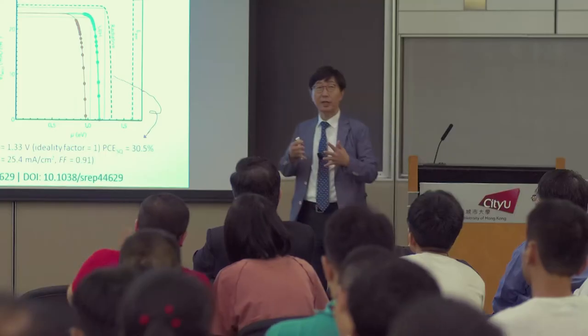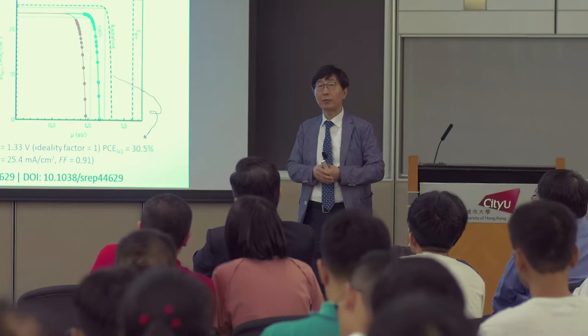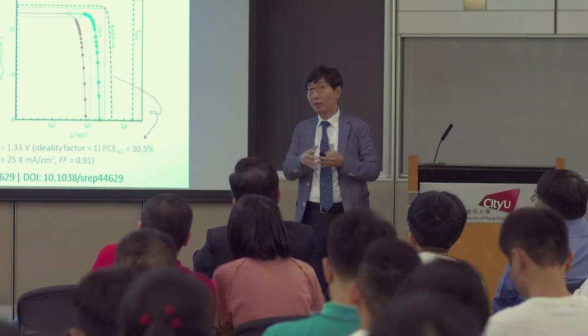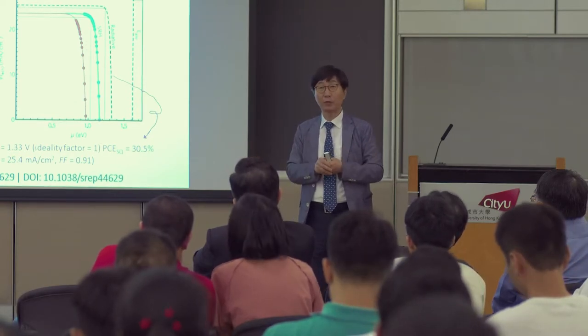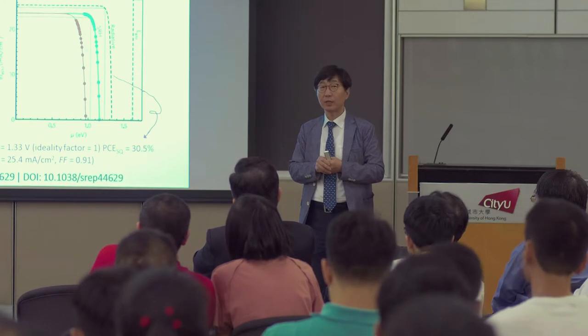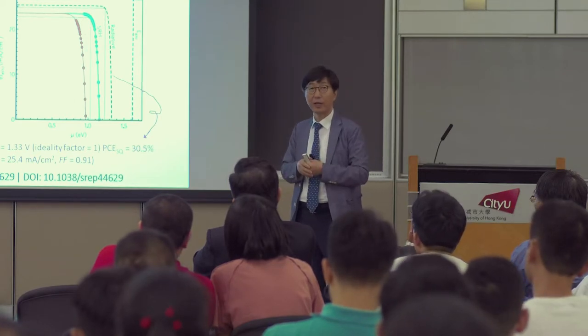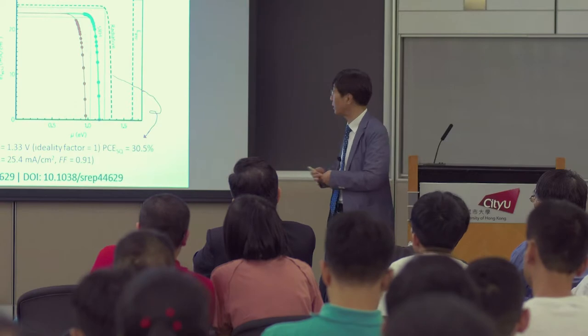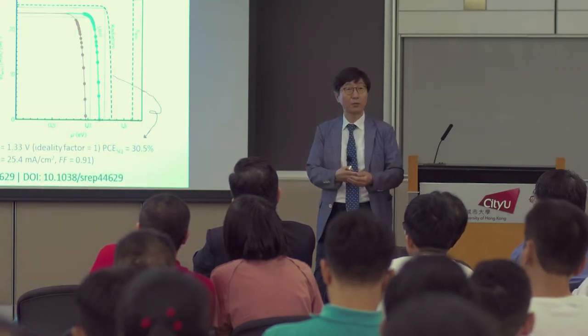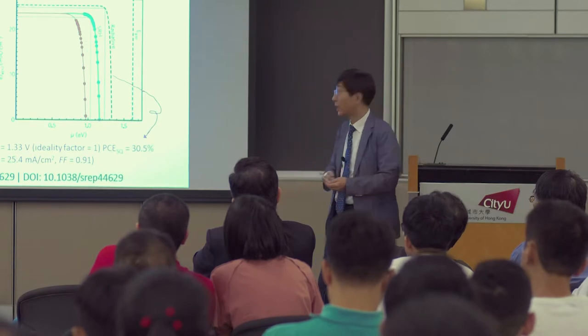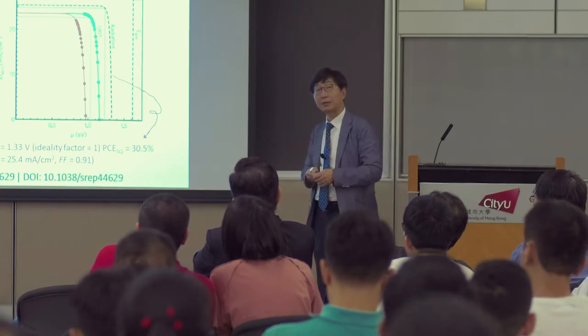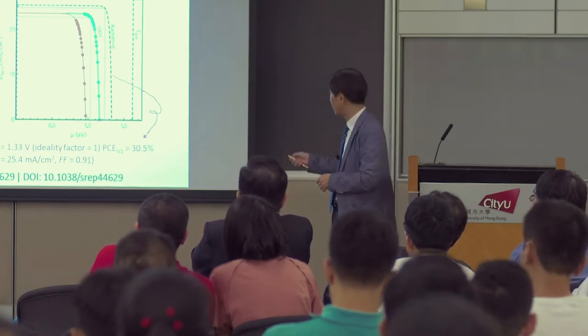So recently, probably if you are working on the perovskite solar cell, usually for high efficiency of 20% efficiency, the open circuit voltage is around 1.06 or 1.07 volt, meaning that you still have a lot of the SRH recombination component.